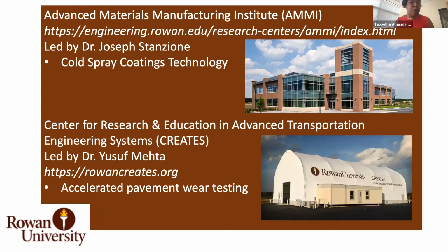And then the other center that I wanted to mention as related to materials processing and characterization is the CREATES Center. It's our transportation center led by Dr. Yusuf Mehta. Among other things, the center has an instrument that does accelerated pavement wear testing. At that facility, they're able to lay down actual samples of the asphalt, modified asphalt, or modified asphalt for heating the pavement for cases where the temperature is very low. They're exploring ways to heat and melt ice using additives to the asphalt. The instrument that's available there is able to do a significant amount of wear testing in a very short period of time. So in about 3 months, it's able to replicate approximately a decade of wear testing.